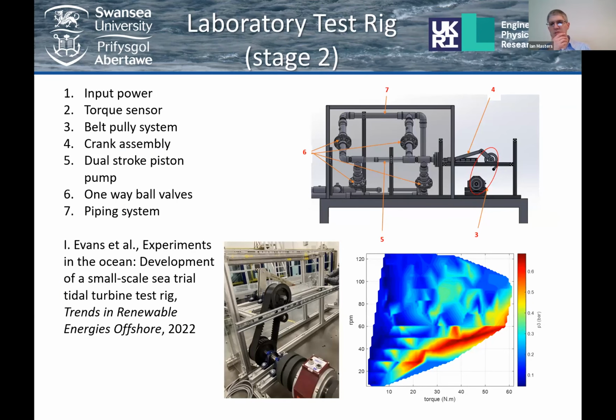Okay, our first real test was to build the power takeoff at small scale in the lab. We've learned a lot from doing this. It's a simple crank arm with a pump. We're pumping water. It's a two-way pump with some one-way valves in it. So we pump on every half stroke. And bottom right of here, there's a mapping of torque, speed, and pressure on that pump. So we can then translate that back into energy generated from the system. The idea is that the pump would then pump water down a pipeline to shore, and at shore you would either use that water for irrigation or similar, or you run it through a hydroelectric turbine to generate electricity.